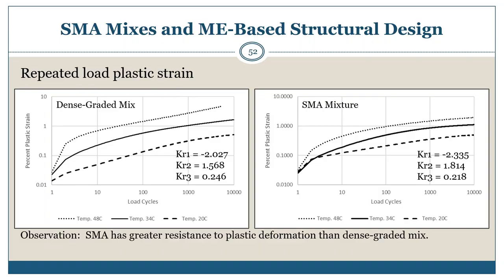Repeated load plastic deformation values are lower in general than the values measured for conventional dense graded mixes because this test does have confinement. So the test results exhibit the impact of higher internal friction of SMA mixtures. In other words, they're more resistant to plastic deformation, resulting in lower rut depths.